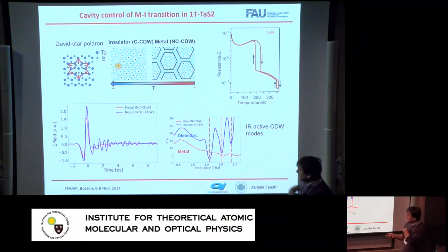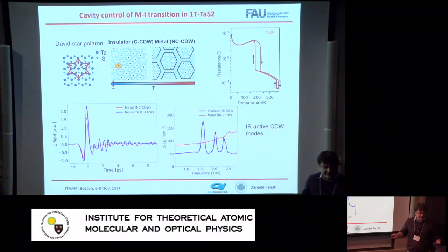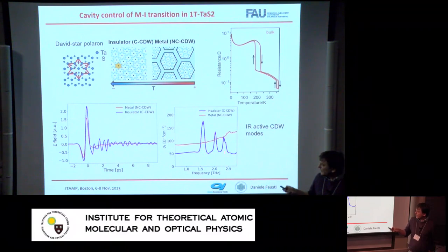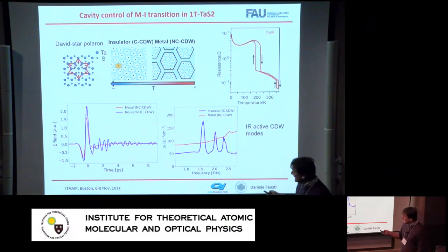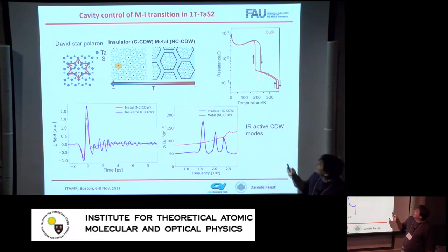We will use this just as plain data. We will not do anything on the data, but of course, you can also extract the optical conductivity, and you see that the optical conductivity has three very sharp phonon resonances in the dielectric phase. But as soon as you increase the temperature and go into the metallic phase, the free charges completely screen the phonon modes, and the system becomes metallic. It's seen in continuous resistivity, and it's also seen in AC conductivity in terms of a Drude peak at low frequency.